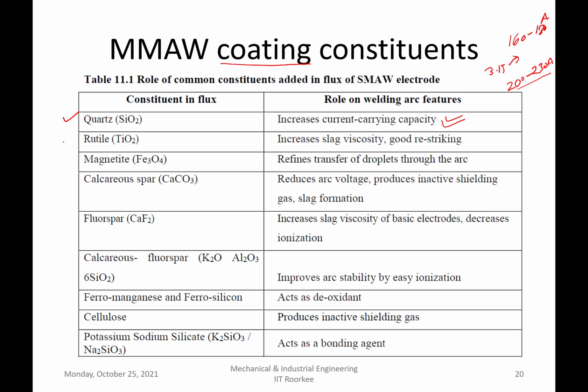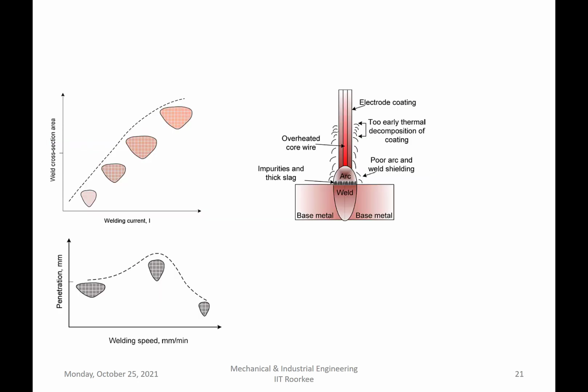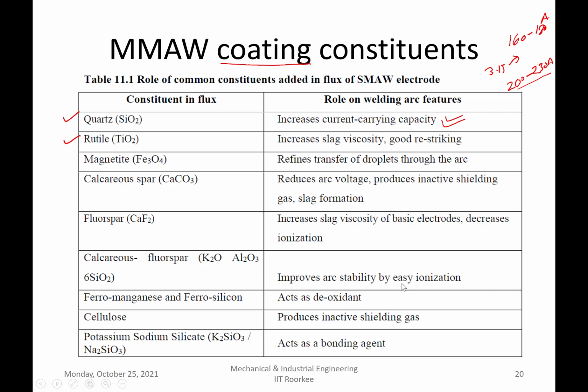Similarly, the rutile, that is TiO2, when added, helps to form viscous slag. Viscous slag is important especially when you are welding in vertical, horizontal or overhead positions, so that the molten metal doesn't fall down. At the same time, because of the good electron emitting capability of titanium oxide, it strikes the arc easily. So good arc striking feature. Magnetite, Fe3O4, helps refine the transfer of the droplets through the arc, so even fine droplets are transferred.